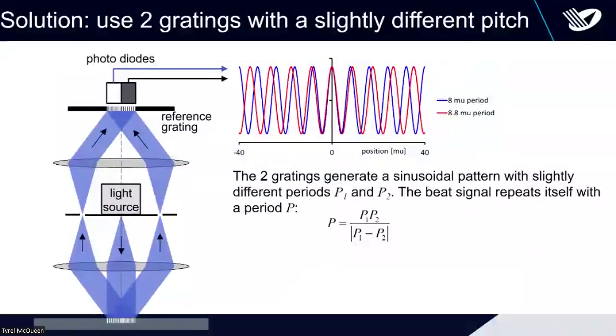There the trick is to use two gratings. So you basically put two gratings in the alignment mark and two gratings here that have slightly different periods, by about 10%. And what you then get in the transmission function is that they are slightly out of phase, and only at the location where you actually want to measure are they in phase, as you will detect the total intensity from both gratings, so the sum of the two. You get a peak here, and that is where your actual position is.